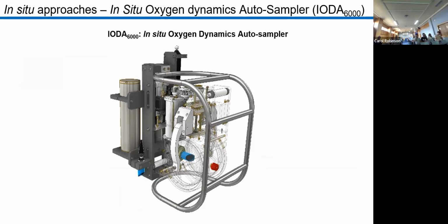To come back to what Matthieu said about the material, the first generation was made with a chamber of 5 liters, but in plastic. Unfortunately, I didn't study physics of materials, and I didn't know the plastic was permeable to oxygen and was a storage of oxygen. Basically, a plastic like polycarbonate holds 6 times the concentration of oxygen than seawater.